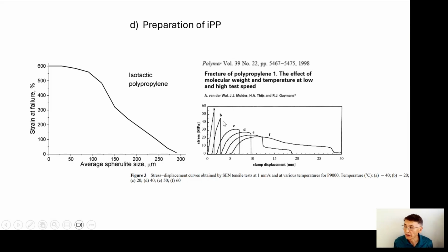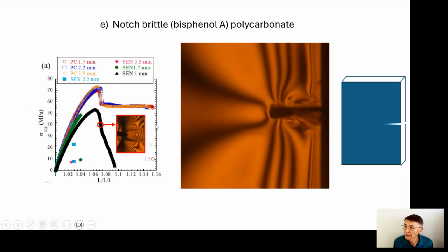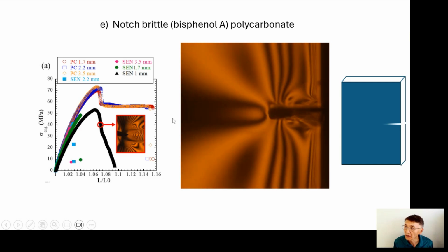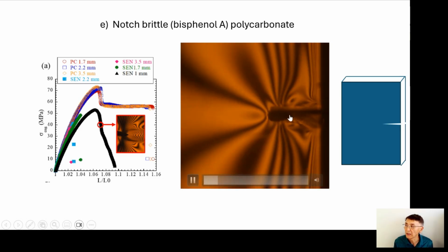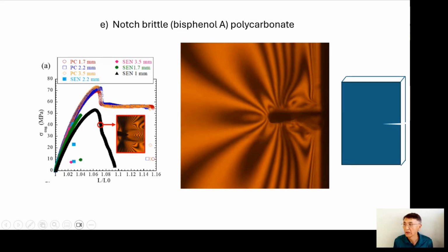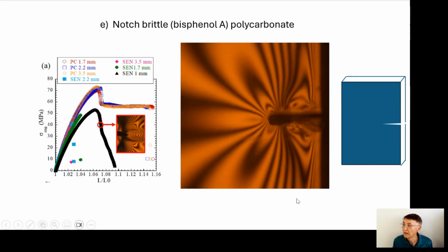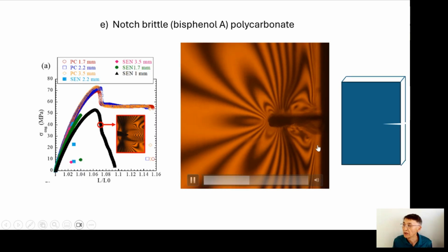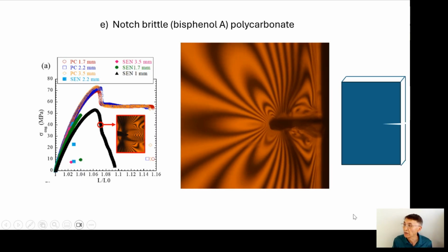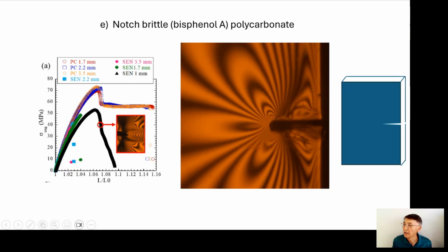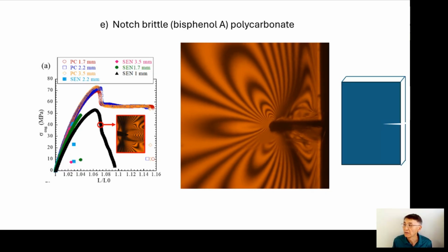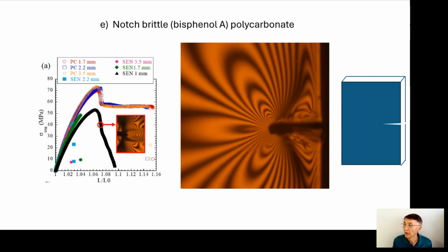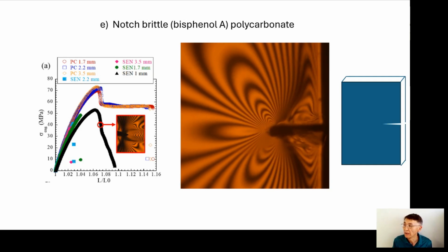And when it's brittle, because Tg is only -10, when it's below Tg, it tends to be brittle. And people use biaxial stretching to solve that problem. So lastly, it is known that even ductile polymers can be brittle in presence of a so-called notch or crack when the sample is thick enough. So this is just a movie showing, now we know how to show it, that even a very ductile polymer like polycarbonate, bisphenol A polycarbonate, turns brittle.